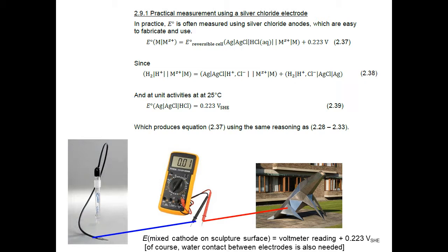Those are easier to work with, and the equations 2.37 to 2.39 use the same manipulation as on page 14 in order to show how we can measure an electrode potential of something relative to standard hydrogen electrode by actually measuring it relative to a silver chloride electrode, and then adding the difference between the standard hydrogen electrode and the silver chloride electrode. So that's how measurements of electrode potential are done in practice.